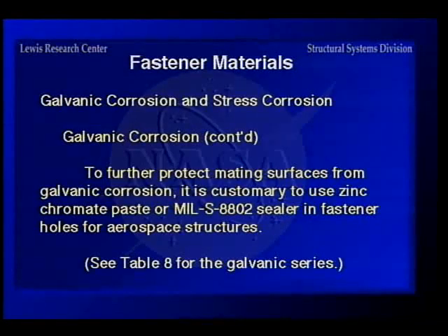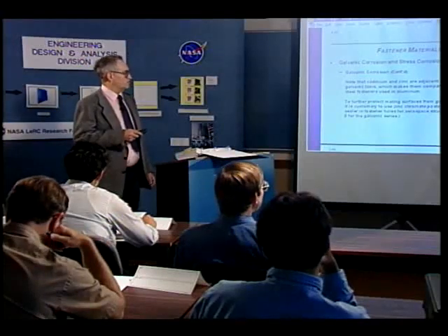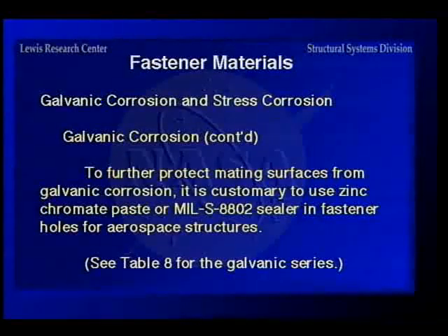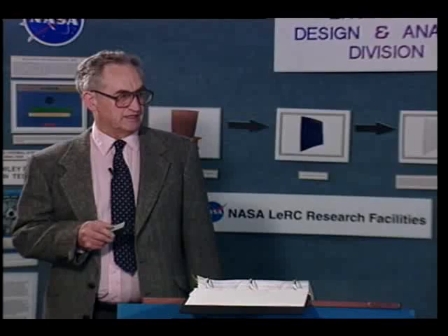And to further protect mating surfaces from galvanic corrosion, particularly where you're putting in rivets, and you pilot drill one piece and then drill it through, you have raw surfaces that are not plated with anything. So you either use a zinc chromate paste, or there's a Mil 8802 sealer that will deter galvanic corrosion.